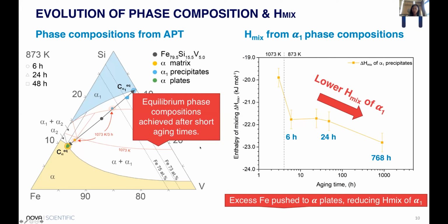Using the compositional data from the alpha-1 phase, we calculate the enthalpy of mixing, H-mix. While the ordered alpha-1 phase tries to get rid of extra iron, the iron is continuously pushed into an alpha plate. This process lowers the enthalpy of mixing by about 3 kilojoules per mole after 768 hours of aging at 873 Kelvin.